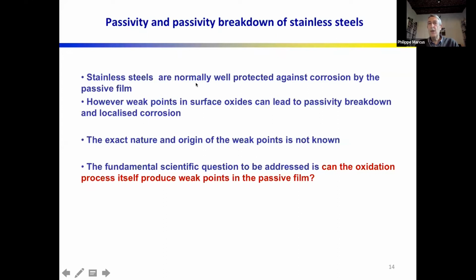Stainless steels are normally well protected against corrosion by passive films, but however, there are weak points that can lead to passivity breakdown and localized corrosion. And the exact nature and origin of these weak points is not known. Of course, we know that if there are inclusions like sulfide inclusions, pitting will start at inclusions. But in very pure stainless steel, and modern metallurgy produces fairly pure stainless steels, there are still weak points in passive layers, which are not just sulfide or other inclusions.